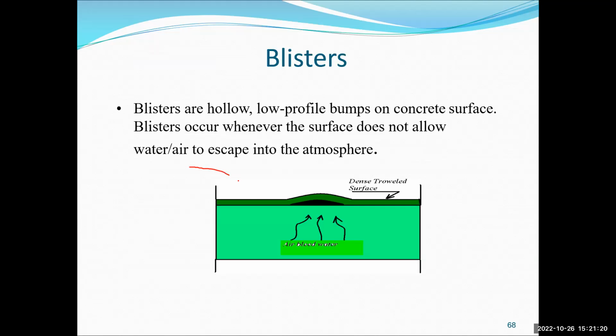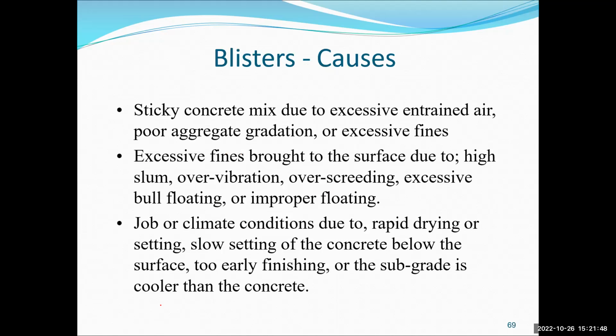Basically, there's the layer here at the very top, a dense layer, which is basically the bleeding water layer. Remember that? The water is going to evaporate and reach the surface. It has no room to go, so it is trapped here, applying pressure and causing this kind of concave surface. We call this blistering. The causes are very obvious. Sometimes you have a sticky mix at the top surface due to excessive entrained air or excessive very fine particles. The fine particles fill up all the gaps and make the top surface completely impervious. Some people overwork the surface with the jitterbug or the finishing, which makes it very dense. So these are the things that may cause it.